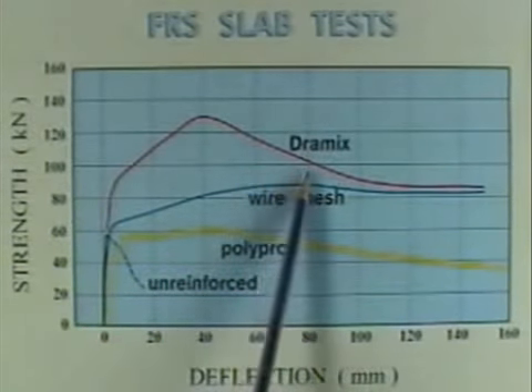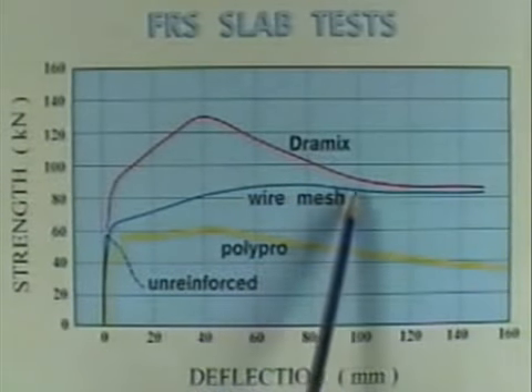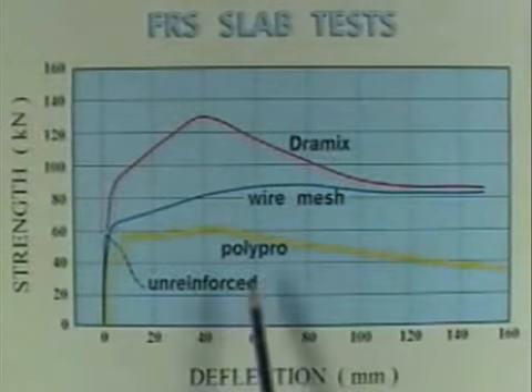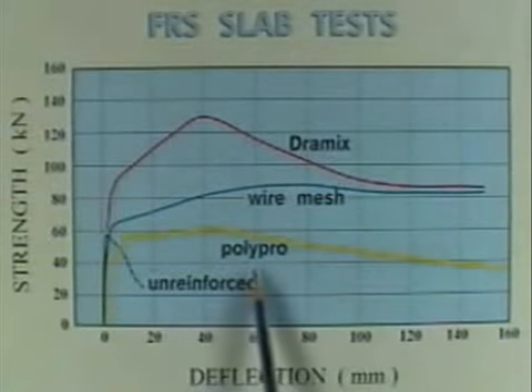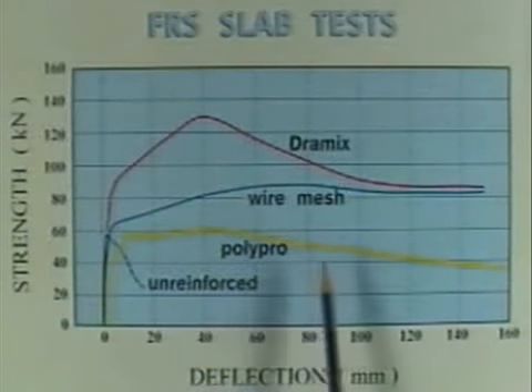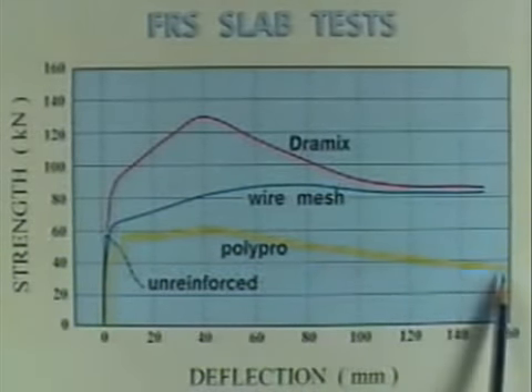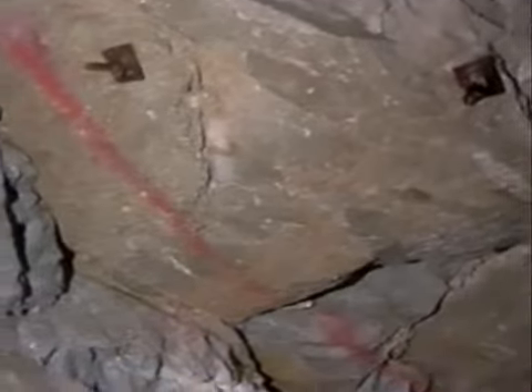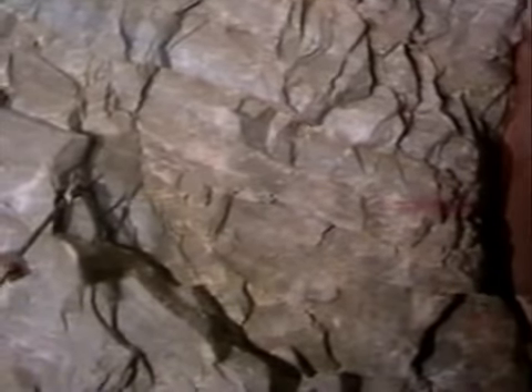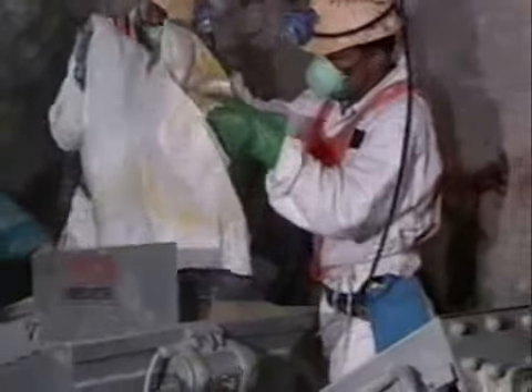The strongest fiber reinforced shotcrete was found to be that based on 40 mm long Dramix steel fiber. A 40 mm long polypropylene fiber produced a shotcrete which also retained more than half of its peak strength. It now remained necessary to show that dry mix fiber reinforced shotcrete of the necessary quality and uniformity could be produced under normal operational conditions in remote parts of the mine.